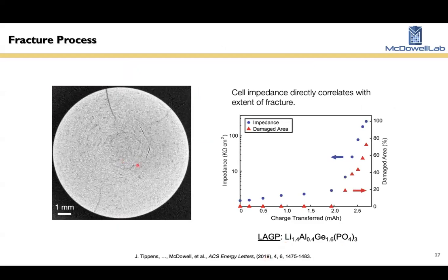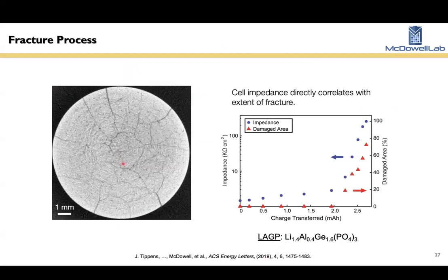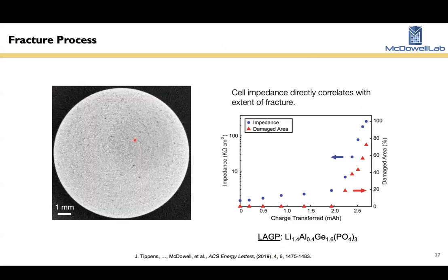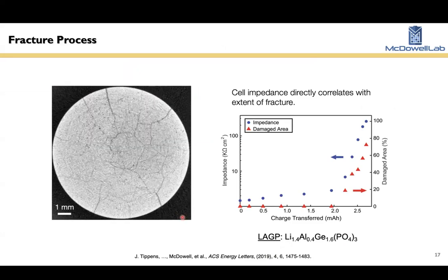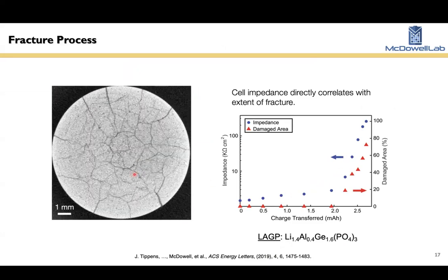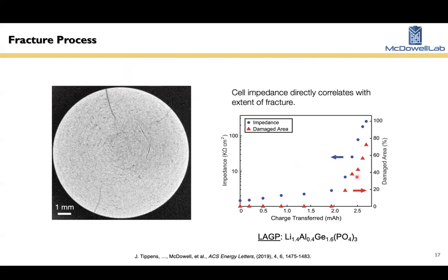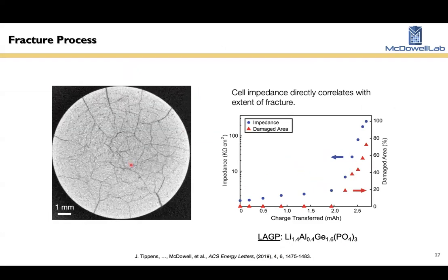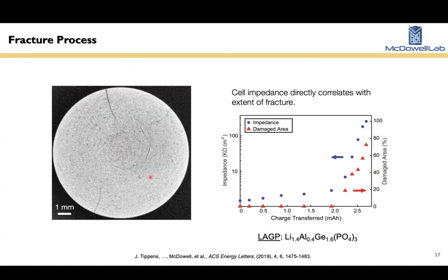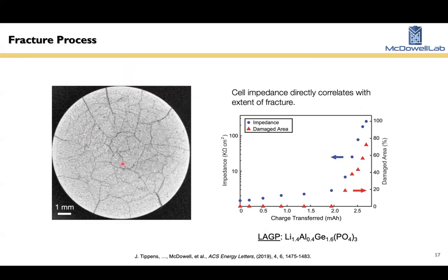And this is a video of this over the long experiment, 40-hour experiment, where these cracks are forming in this pellet. And we found by quantifying how this relates to the impedance, the impedance starts increasing when you have these cracks growing, not when the interphase is forming. So the cracks are really what are detrimental for the impedance.